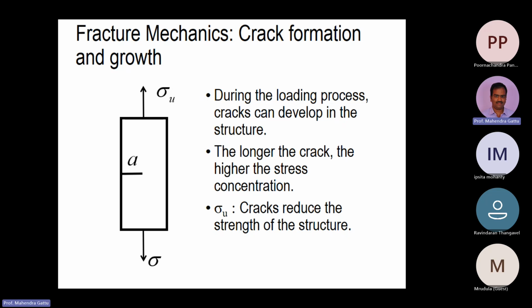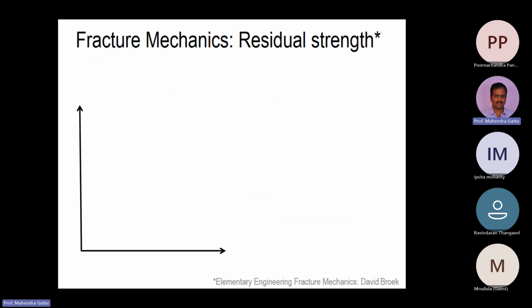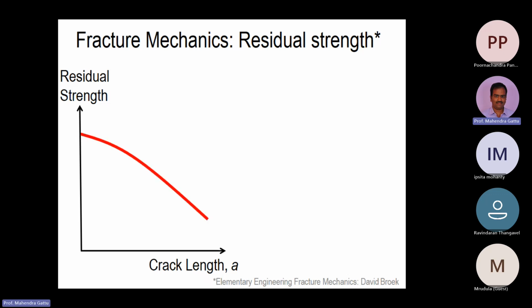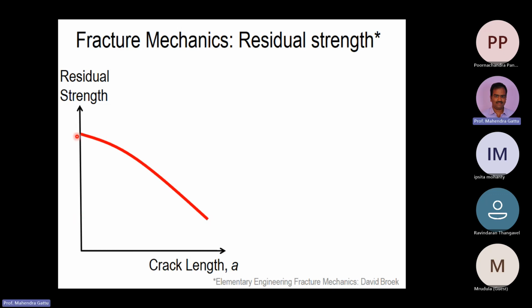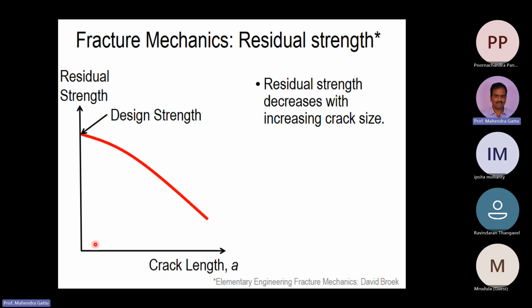Okay. So if you do experiments, what we find is, depending on the crack size, the residual strength reduces. So this is the relationship between crack length size in the material, the structure, and its peak load. So as we keep increasing the crack length, the strength of the structure reduces. So this has been established experimentally. So without any crack length, we have our design strength that is given by the strength of materials. But in presence of crack, we have some reduction in strength.